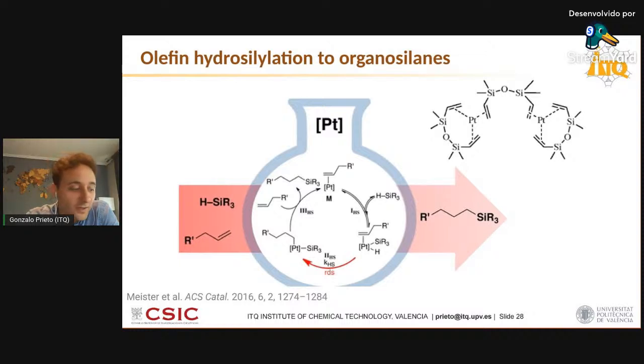This is a platinum catalyst with this type of siloxane organic ligands. That's a classical hydrosilylation catalyst. Very active in liquid phase. Very selective, but not so stable. So they are prone to decompose into, for instance, colloidal platinum particles, which then contaminate the organosilane products, giving them nasty colors and, of course, contributing to a net metal loss from the reactor, a loss which, in the case of a metal like platinum, one should not handle at industrial scale.